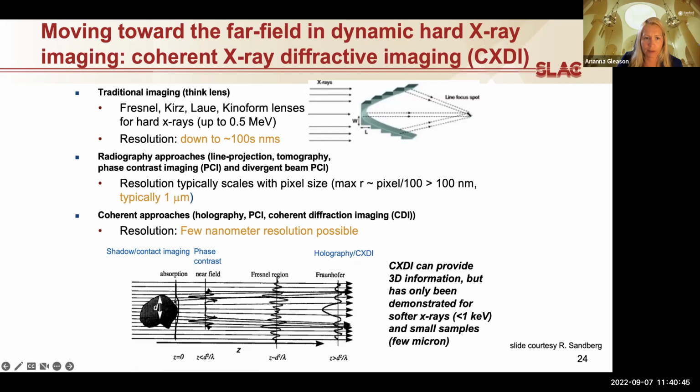focus, if we look down here at this bottommost graphic, there are different sorts of fidelity you're able to extract. Spatial fidelity, certainly less than a micron. That's where we're going to be focused, in the Fresnel to Fraunhofer region, in looking at these void collapse images. We're hoping to get, of course, a few nanometer resolution. The best we've done so far in a shock compressed material is 400 nanometers, which is still better than a micron. You can still claim submicron.